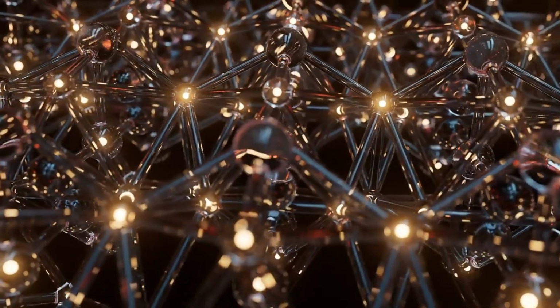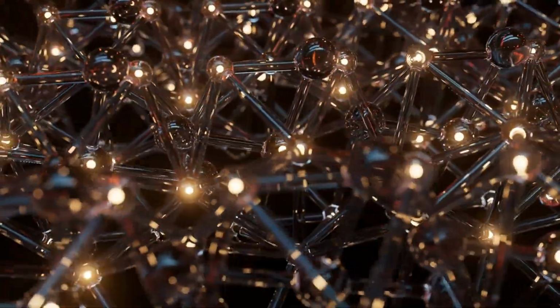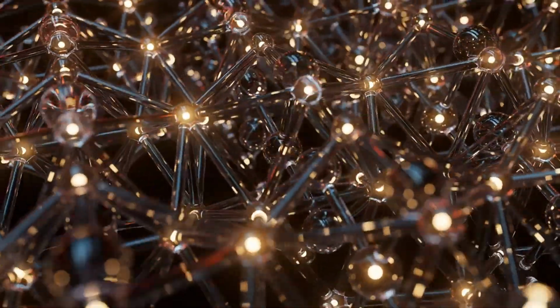Charge balance and electrostatic interactions are also critical factors in plasma crystal formation. Each dust grain is negatively charged, resulting in strong Coulomb repulsion between neighboring grains. However, the surrounding plasma ions and electrons create a shielding effect known as Debye screening, and this weakens the electrostatic repulsion over distance. This interaction follows the Yukawa potential. Additionally, ion wake effects contribute to plasma crystal stability. As positively charged ions flow past the dust grains, they create localized regions of excess positive charge behind each grain. This can generate weak attractive forces that help stabilize the crystal lattice, counteracting some of the repulsion from the Coulomb forces.